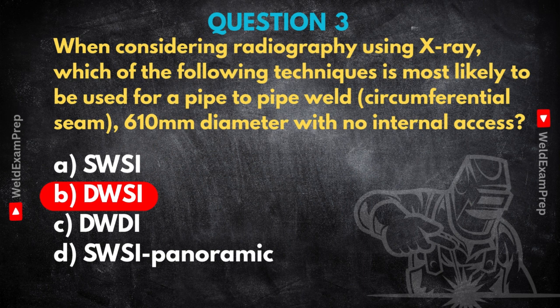SWSI panoramic. Fantastic technique for circumferential welds. Gets the whole thing in one shot sometimes. Uses a special source inside the pipe that radiates outwards 360 degrees to film wrapped around the outside. But again, it needs internal access to place that source. No access, no panoramic. So DWSI becomes the logical, practical choice for this scenario. That really shows a problem-solving side of inspection, doesn't it? You're not just following a procedure. You're figuring out the best way to apply the right technique, given the real-world limitations.